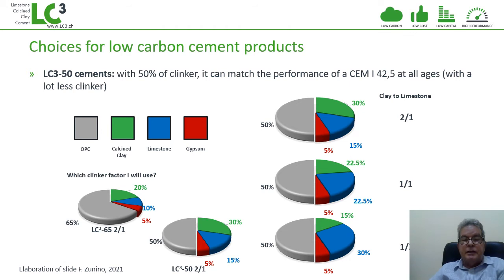The typical traditional LC3 consists of 50% of clinker, 30% calcined clay, 15% limestone, and 5% gypsum. This cement can match the properties of a CEM I 42.5 at all ages. However, you can make different blends, different combinations. You can change the proportions between calcined clay and limestone, you can increase the clinker content. So there are many, many choices depending on what you want to do.